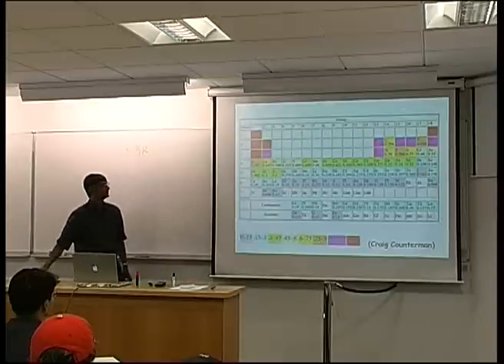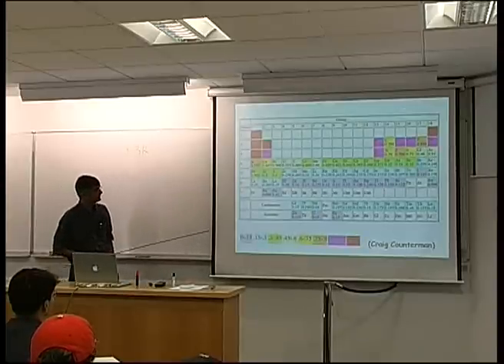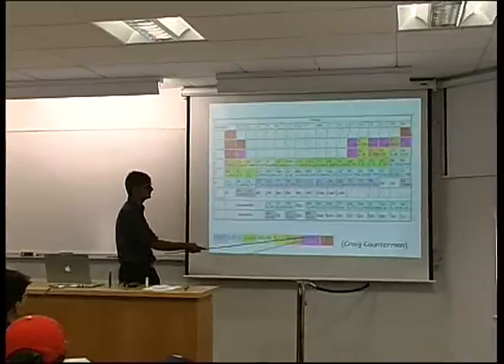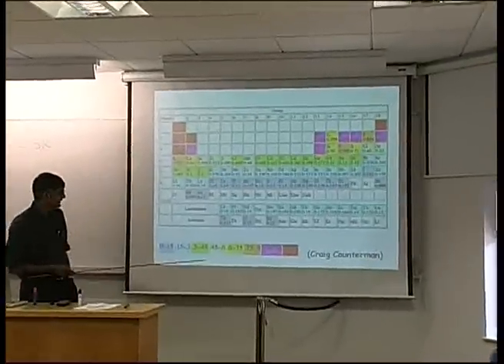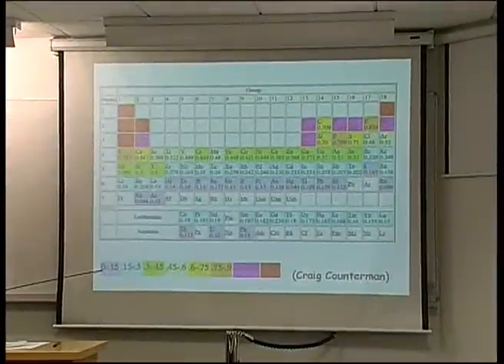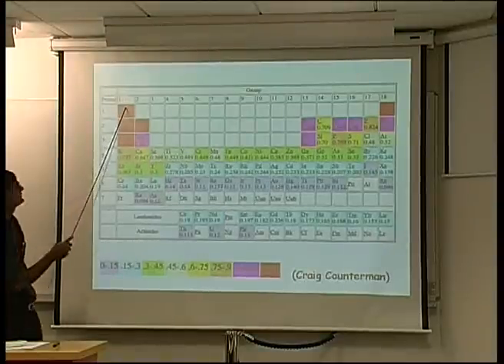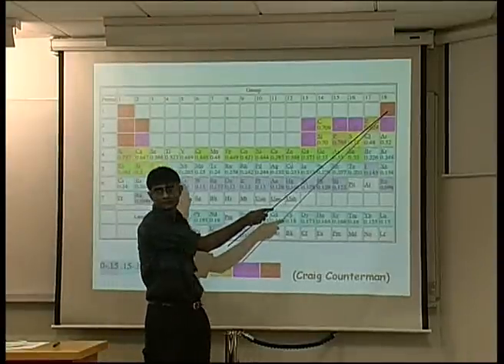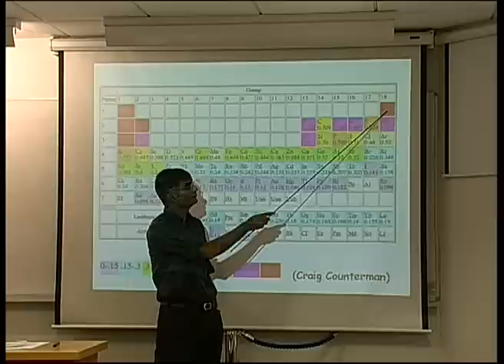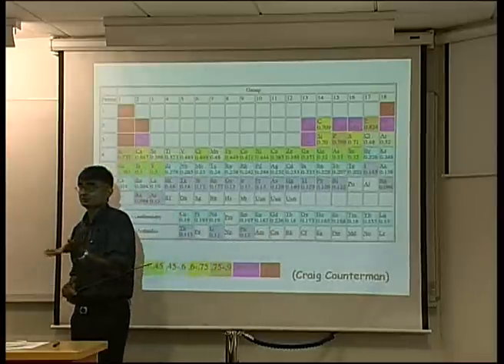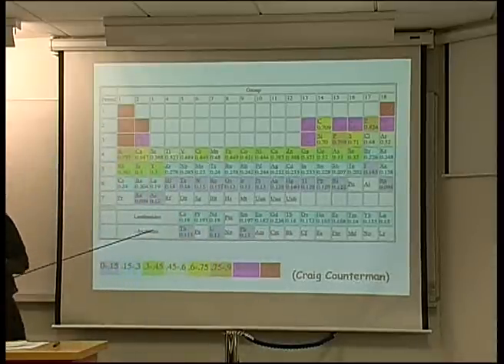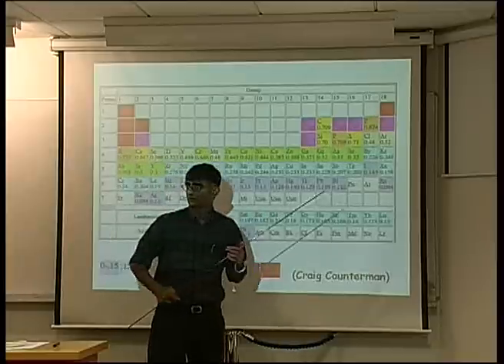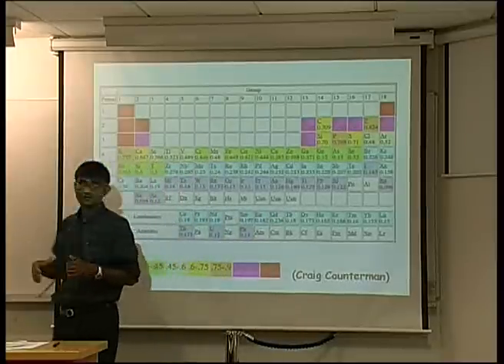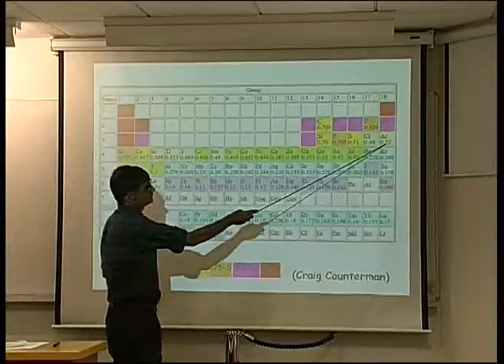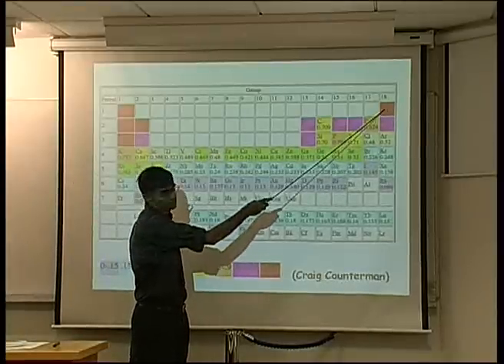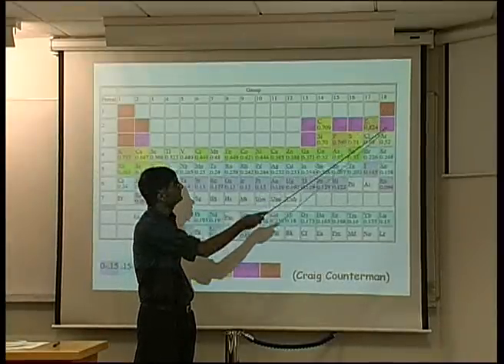Just to give you an idea of specific heat capacities, this is a periodic table, and the red color means a very high specific heat capacity. This is hydrogen, this is helium, which have very, very high heat capacities, and that's why when we're using gas to quench materials, we use helium because it can absorb a lot more energy than, for example, argon over here. This is about 10 times greater heat capacity than argon.